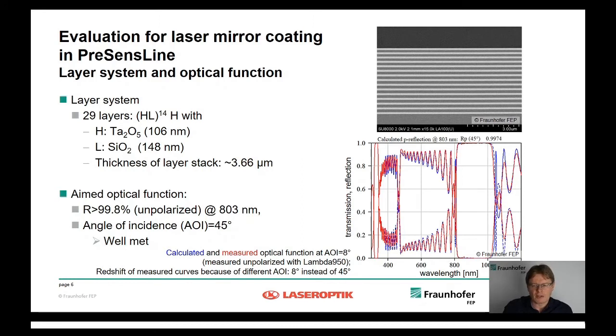We measured actually at 8 degree angle of incidence, so this leads to a redshift, so the maximum here is at a higher wavelength than the 803 nanometers. But we calculated the reflectivity at 803 nanometers at 45 degrees to be this number, so higher than what was in the specification.